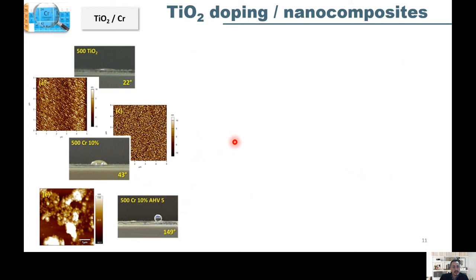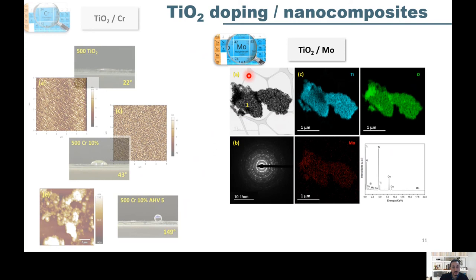X-ray mapping for titanium dioxide modified with molybdenum shows that there is a homogeneous distribution of molybdenum throughout the polycrystalline films. For these types of films, we verified superhydrophilicity behavior at various concentrations of molybdenum.